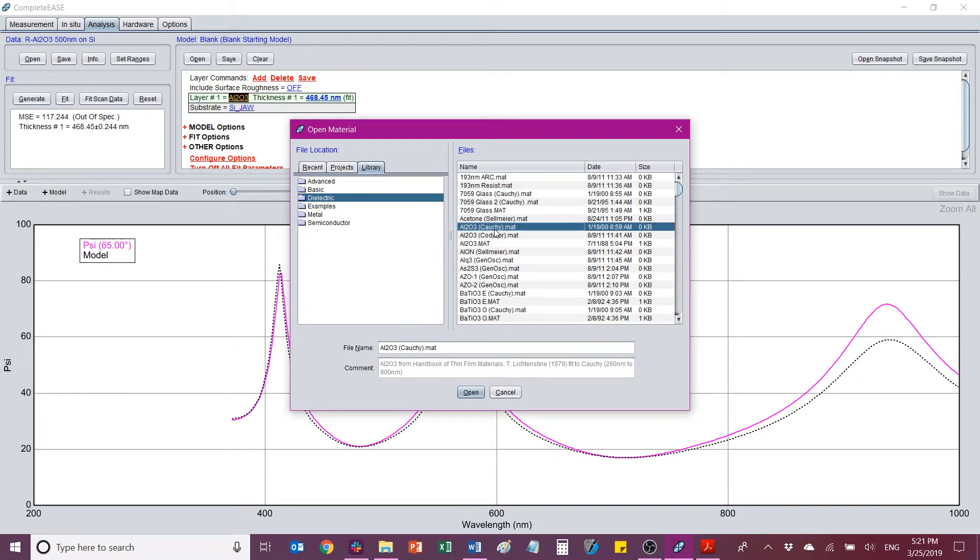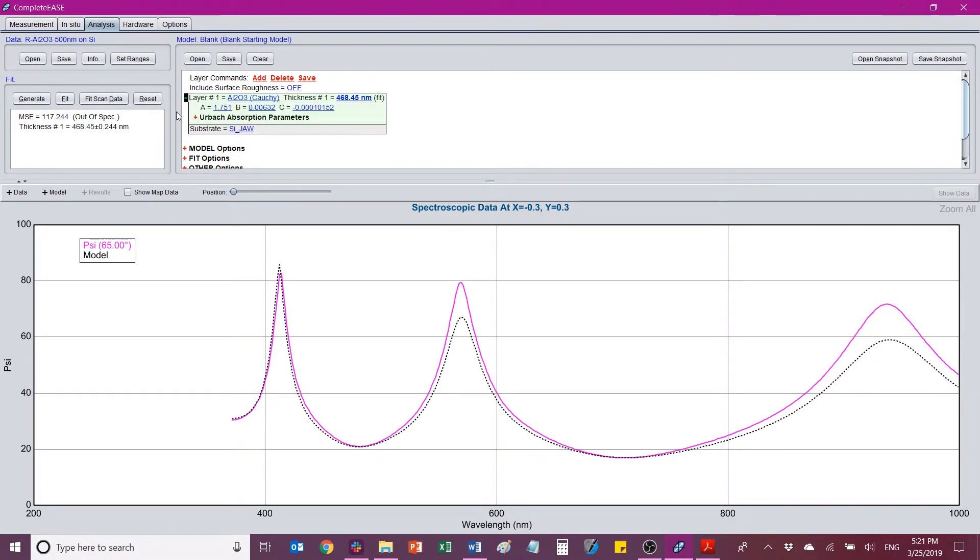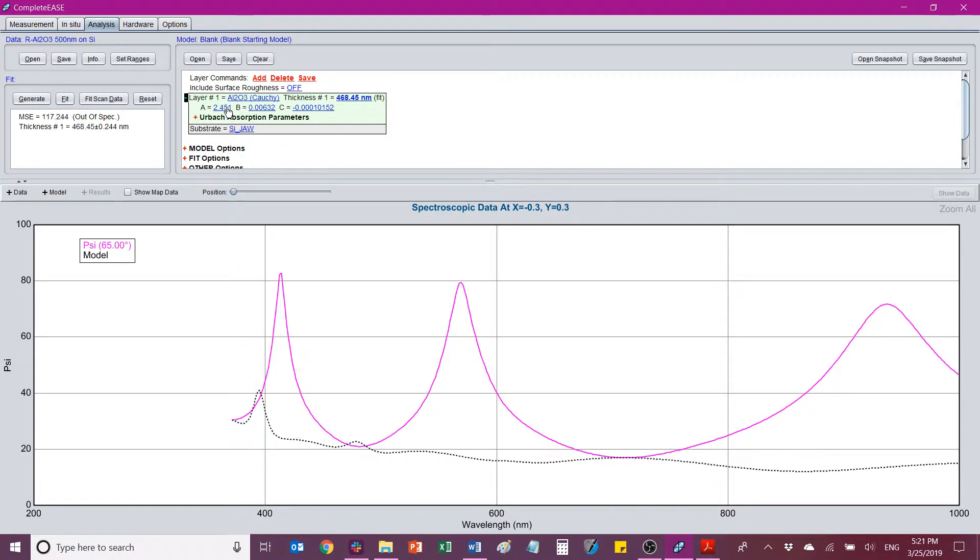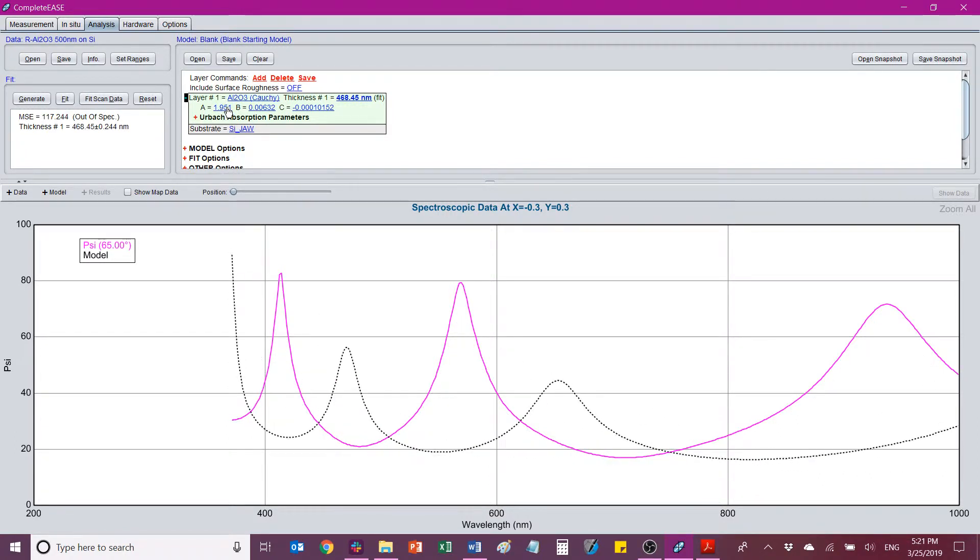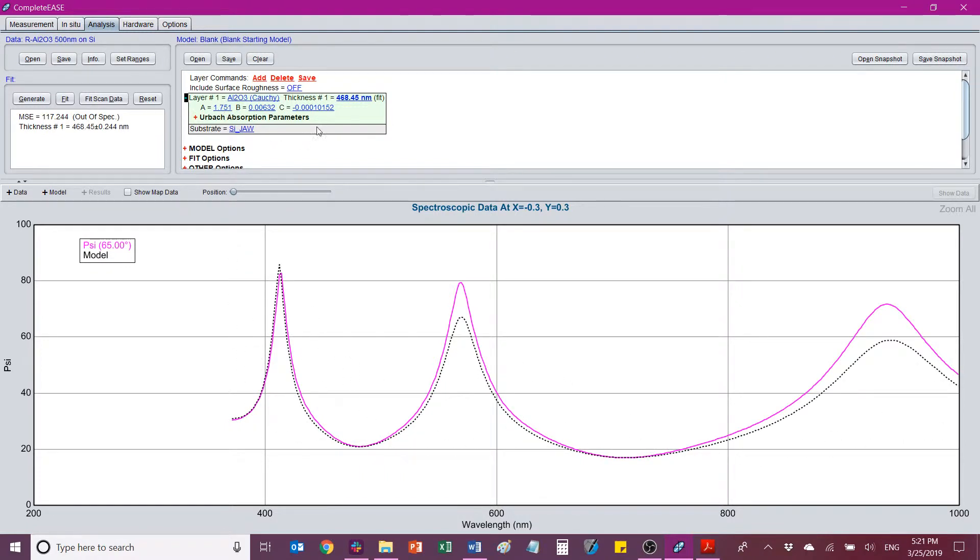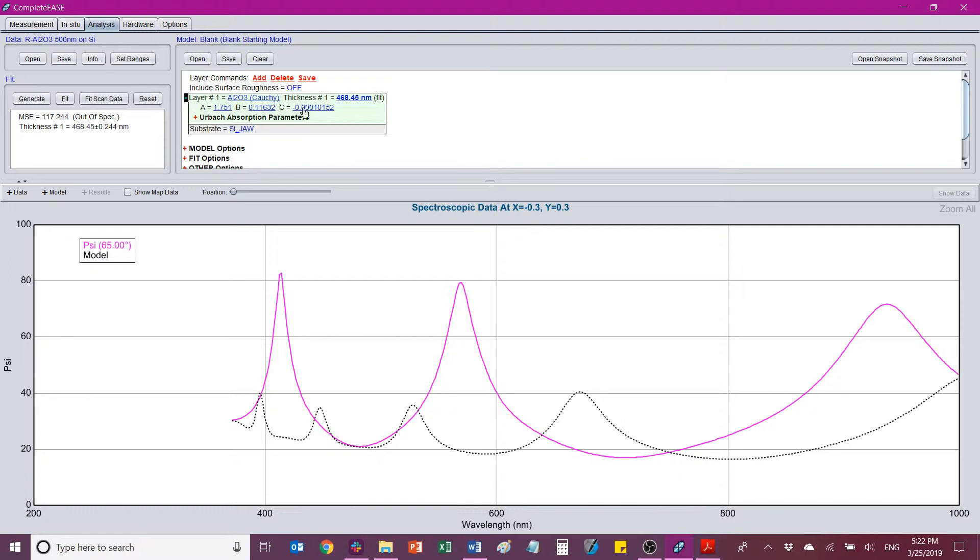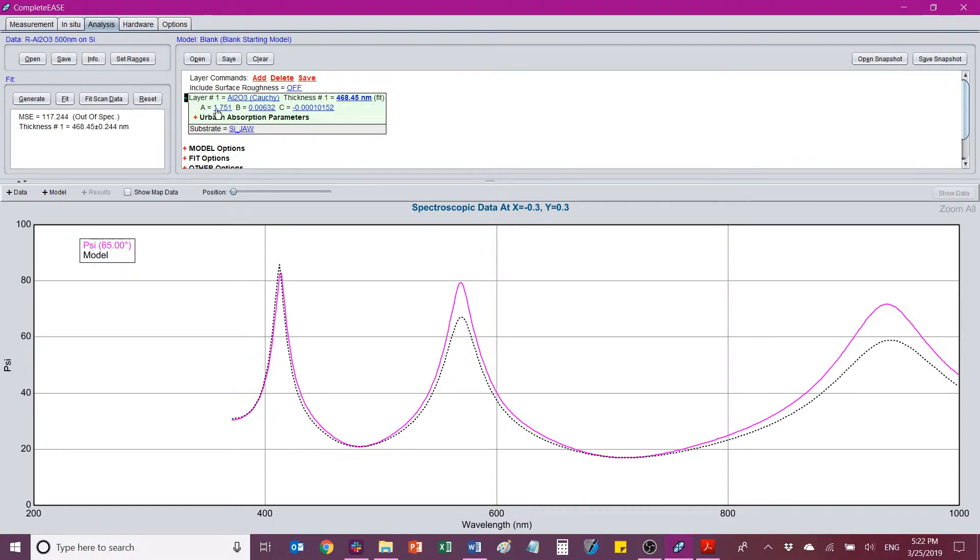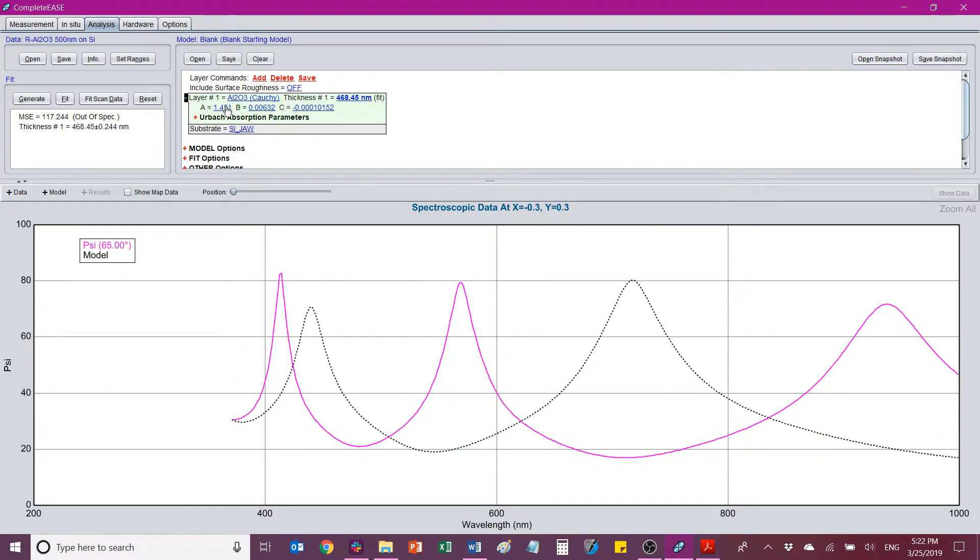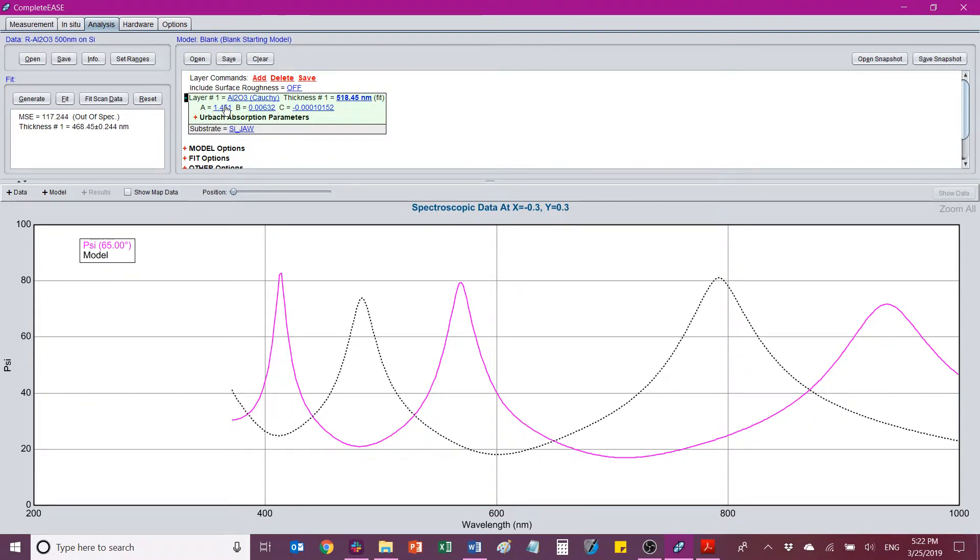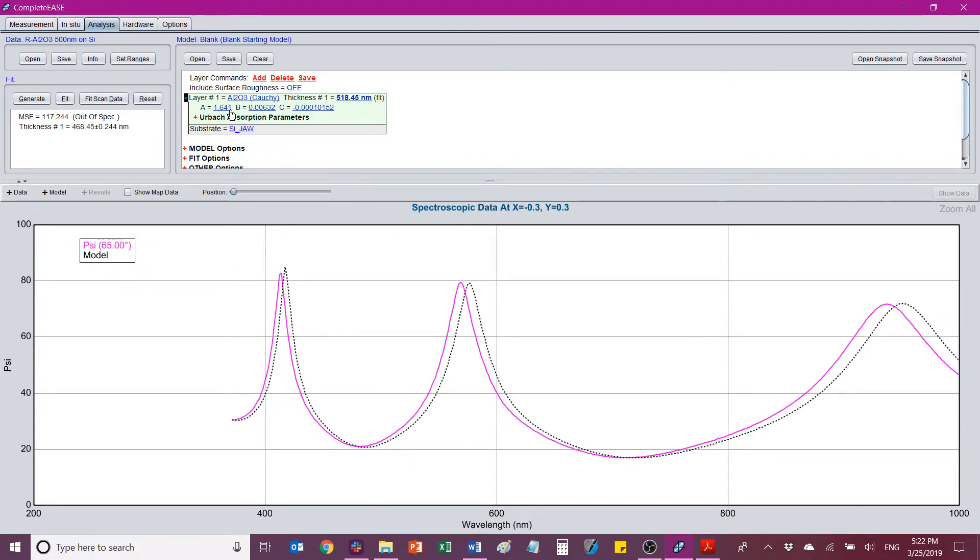The simplest one to use in this case, because it's transparent, is a Cauchy equation. So I'm just going to choose Cauchy. And as soon as I do that, I get this little plus that I can open up. And now I have access to the coefficients in the Cauchy equation. So in addition to fitting the thickness, I can also fit these values as well. So let's leave thickness where it is and just roll this value thicker. And we see that the peaks move to the right as I go up and they also get smaller. Then there's this B coefficient, which kind of widens these in addition to moving things forward and reducing their amplitude. What I'm going to do is I'm going to play with this a little bit and see if I can get these to fit. Not quite. Let's make this a little thicker. And then let's make this a little higher.